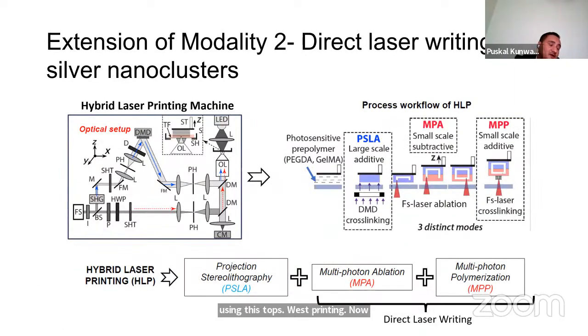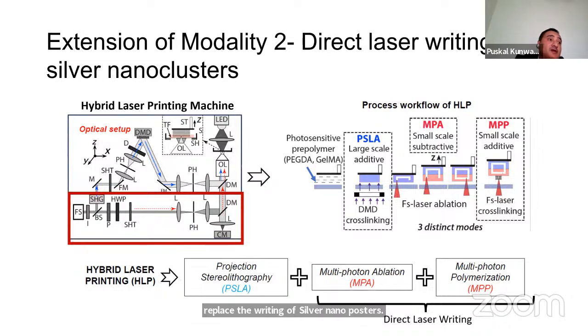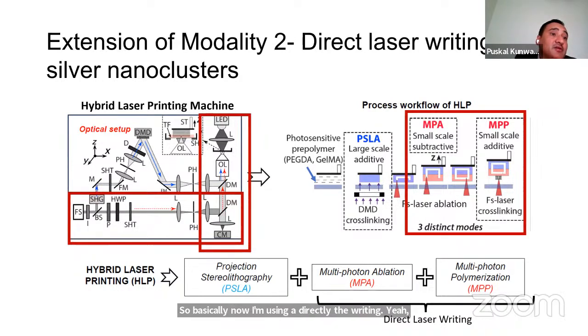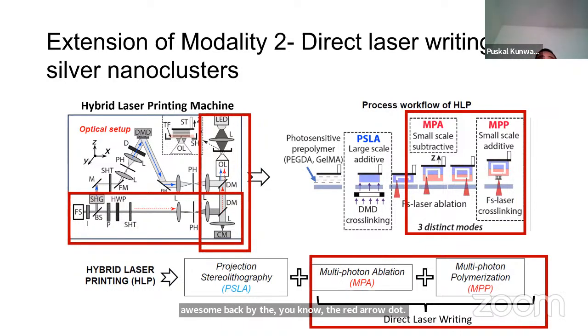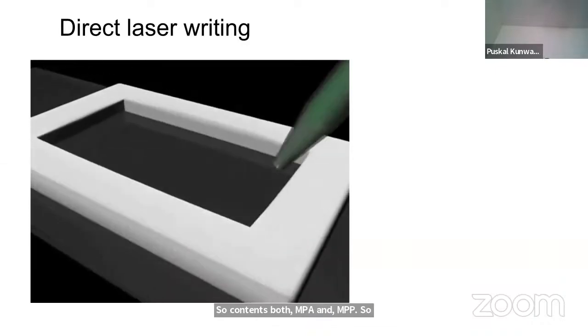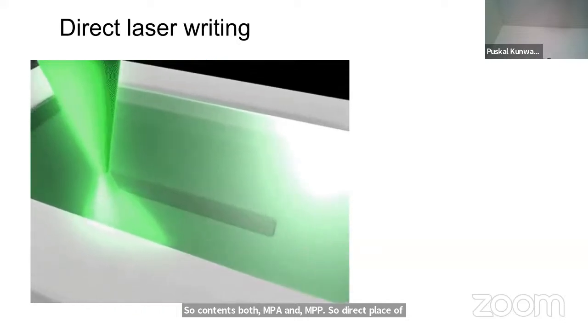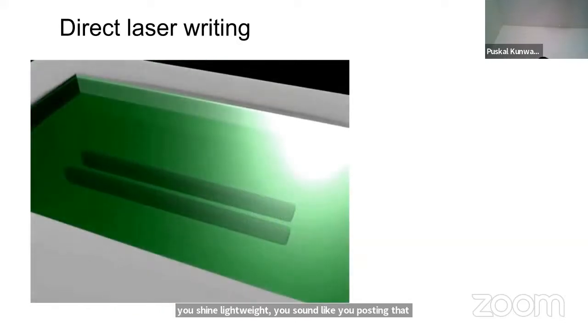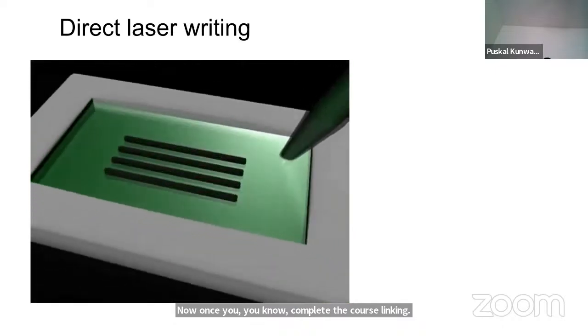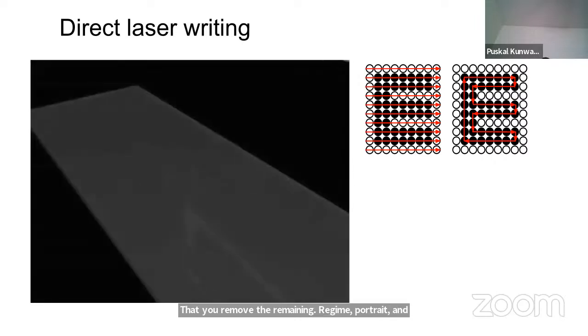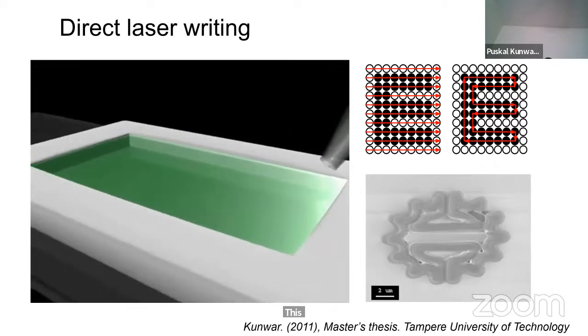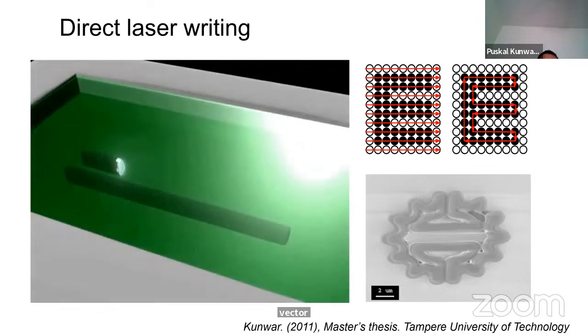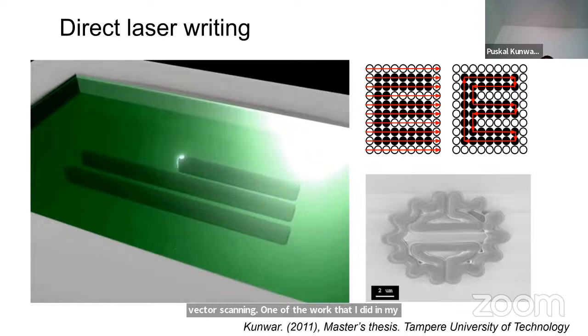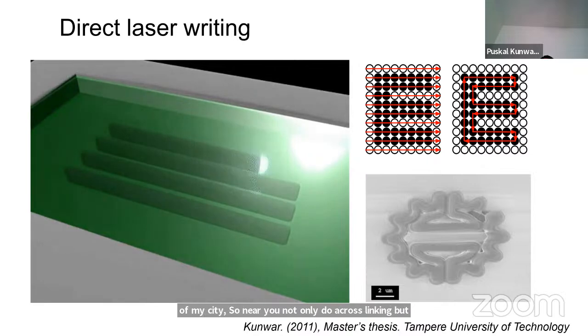Now another extension is modality 2, where I did a direct laser writing of silver nanoclusters. So I'm using direct laser writing on the portion marked by the red arrow, which contains both MPA and MPP. In direct laser writing, you start with the resin, then you shine light, and wherever you shine light, you cross-link it. Once you complete the cross-linking, you remove the remaining photoresist, and what's left is your structure. This approach of scanning can be raster scanning or vector scanning. In one of the works I did in my master thesis, I printed a micro logo of my university, Tampere University of Technology. So you can not only cross-link, but also ablate structure from a precise location.